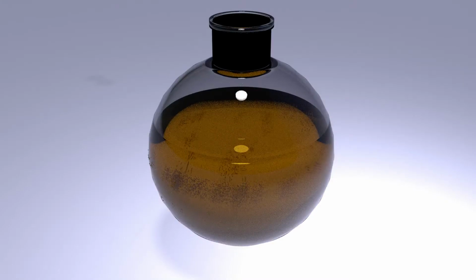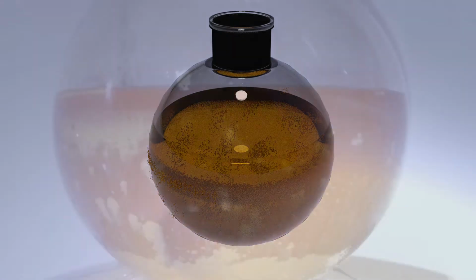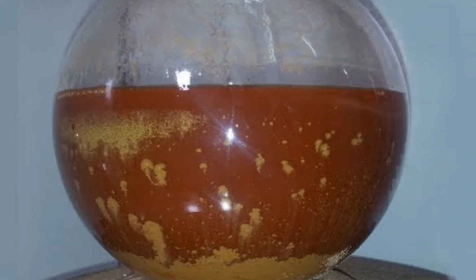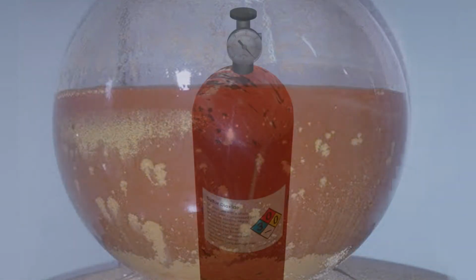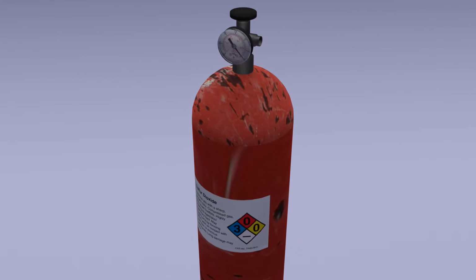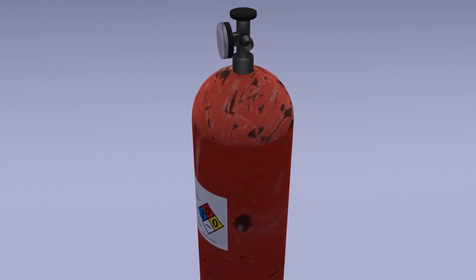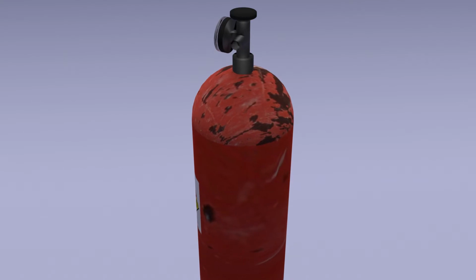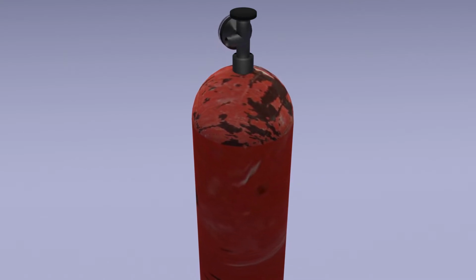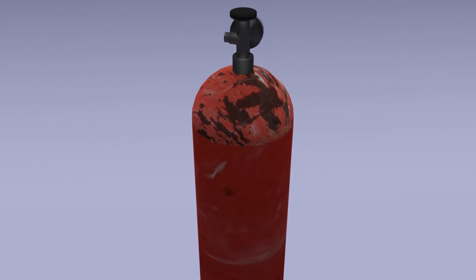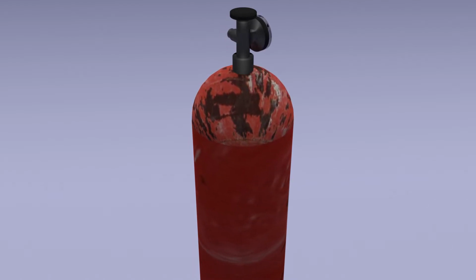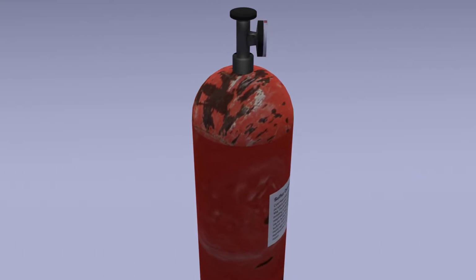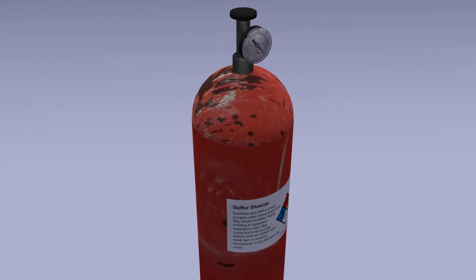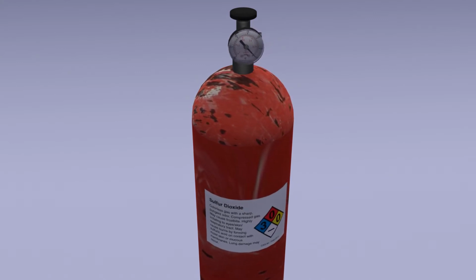After the metal is dissolved into solution, the gold can then be selectively precipitated out of solution, leaving all the other metals dissolved. There are 2 different precipitants that are traditionally used. For large-scale refining, sulfur dioxide gas is the traditional choice. This is both very corrosive and very toxic. Surprisingly, this is actually a good choice for large-scale refining, because large-scale refiners have the hoods, ventilation, and scrubbers to handle this gas, and because the sulfur dioxide produces heavy gold particles that are easily filtered.